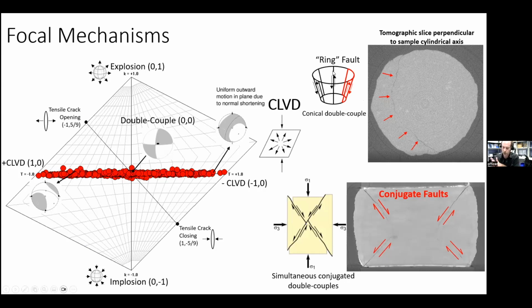The other way you can get CLVDs is if you have a double couple, or a shear fracture, on a curved surface. And we do see shear fractures on curved surfaces. So this is like a ring fault here. And you can also have two conjugate shear faults that happen simultaneously, which can sort of masquerade as CLVD.